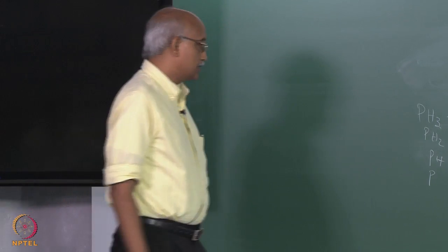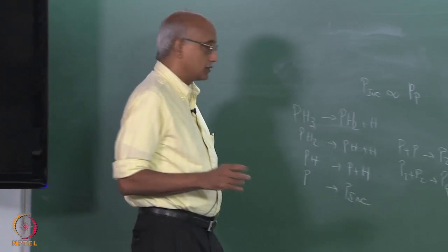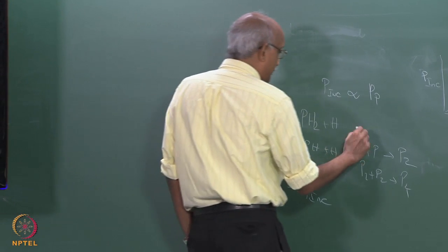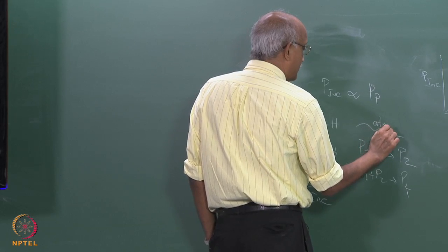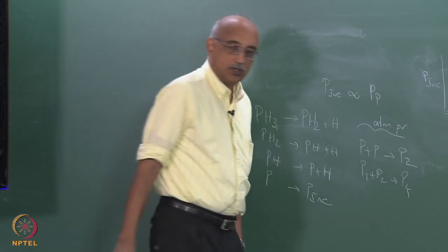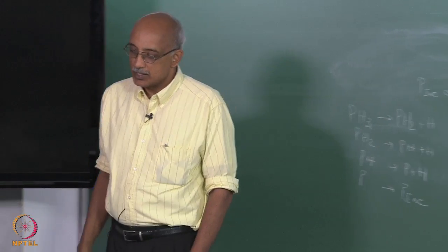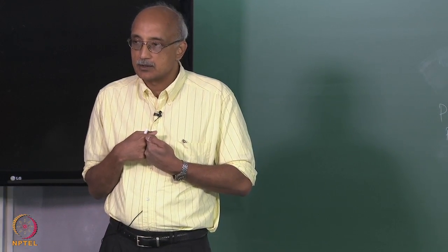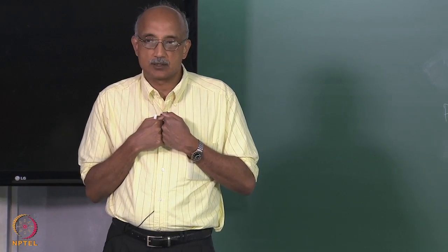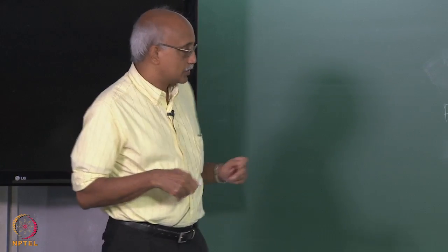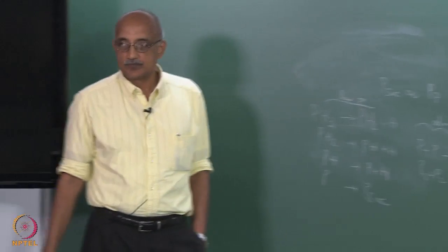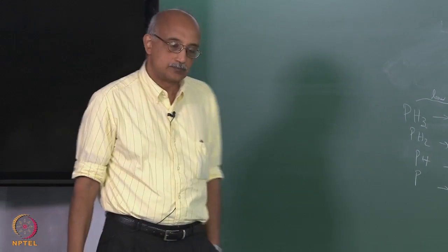Now, the interesting thing is that if you look at the effect of total pressure, these reactions are more likely to happen closer to atmospheric pressure. Essentially, as you keep increasing the pressure, the molecules get forced together and start combining in forms that normally they would not. So, in the low pressure case, these are the more likely set of reactions.